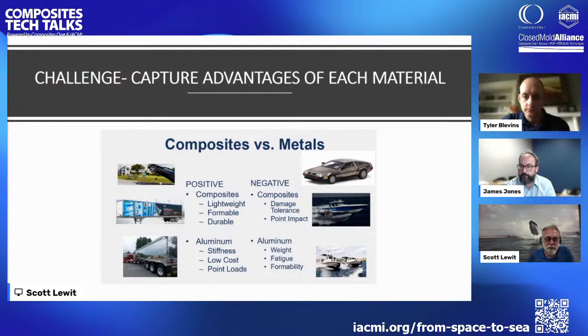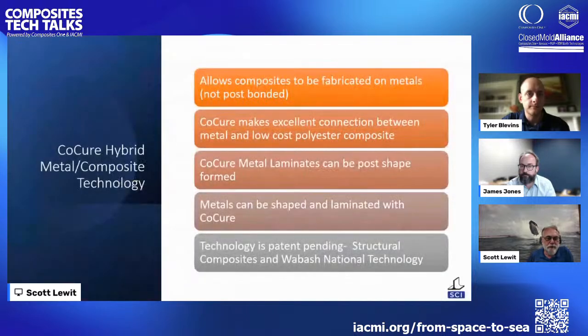We made a discovery again with CoCure. What we're trying to do is get rid of the negatives of each material and stress the positives. Okay. And we discovered that by changing the CoCure formulation again, we can change it from a coating to an adhesive. By making it change from not stick to stick, it can really stick. So we can spray it right onto metal surfaces, just like we'd spray gel coat, but now it's an adhesive coating. We spray it on the metal, and then just like laminating to gel coat, you laminate on the metal. That's it. It's just that simple.